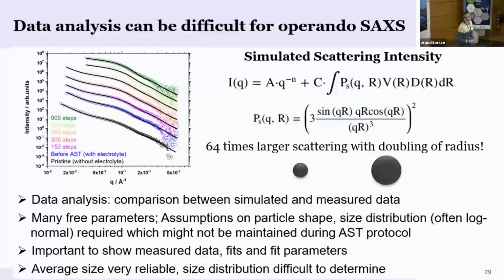One thing we are fighting a lot with in the data analysis is, as said, the average particle size is a very nice outcome and it's very reliable. But to get size distribution changes with small angle X-ray scattering operando is not that easy. And it's mainly because the scattering changes a lot. If you have smaller particles, they have very little scattering, and it's changing with the volume to the square.